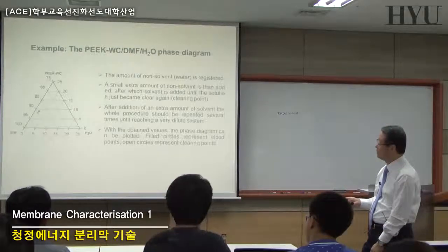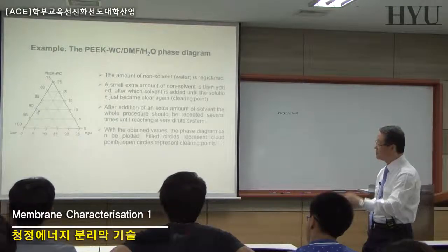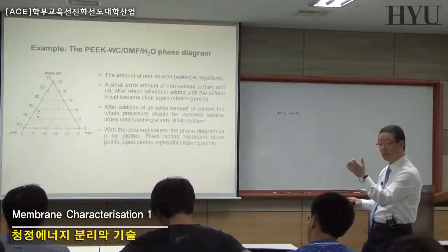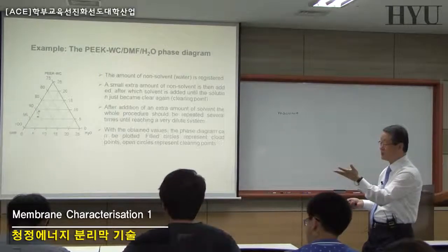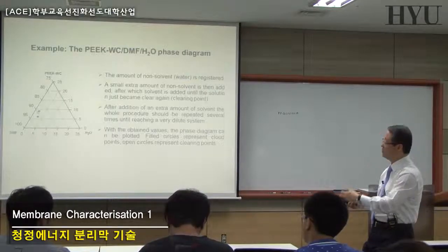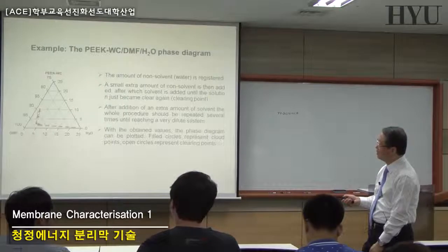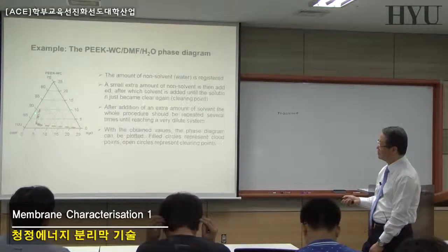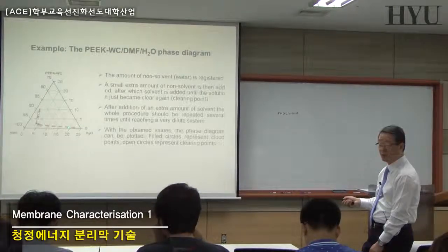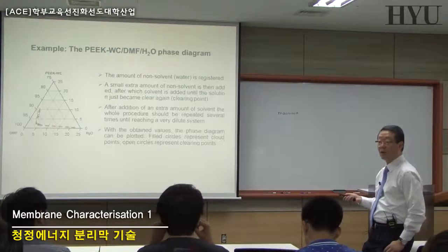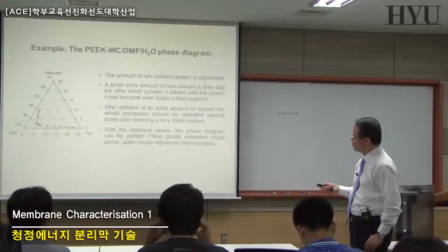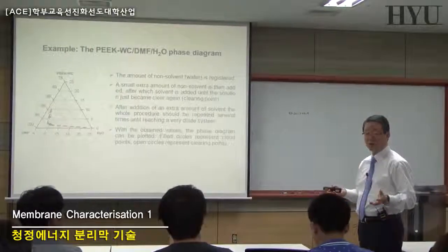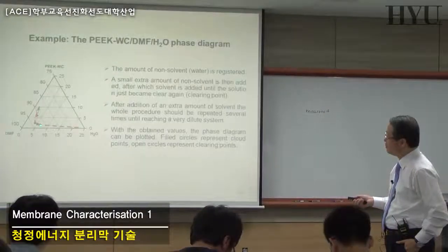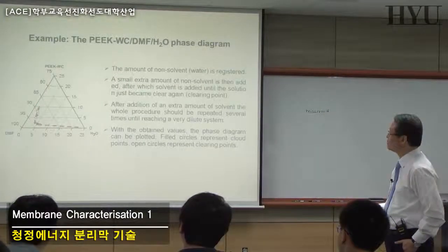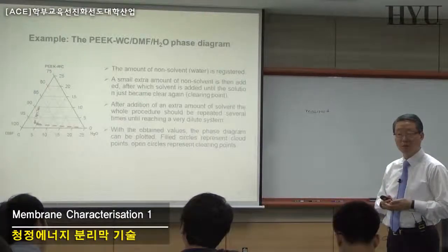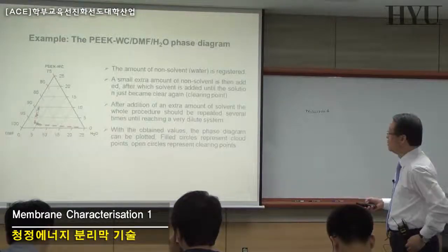What you do is add the water and get the cloud points. And the cloud points might move by changing your polymer concentration. If you have a second composition, third composition, stuff like that, you can connect them all. So this is the line where your binodal points are. When you determine your cloud points by changing your polymer concentration and then connect them, these are the binodal points. It's very difficult to measure the spinodal points, so you just determine the binodal points in phase diagrams.